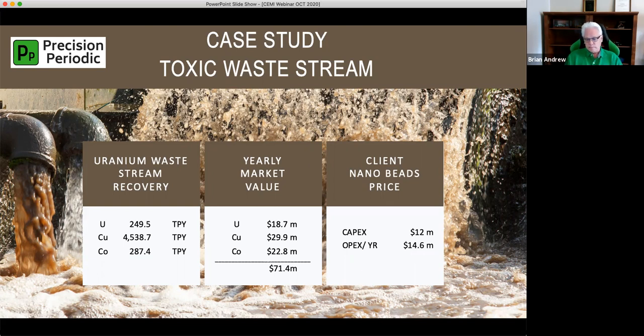And so it turns your waste into a profit center, which is pretty exciting. And this is true for the tailings we've looked at for acid mine drainage. When you go look at a tailings problem in America, you usually find it's leaching from a huge pile of something left there. And in America, for example, gold mines, a lot of the piles, the waste, the tailings are sulfide-based ores because they're difficult to handle. And with this process, you can go in and process the sulfide ores, keep the gold, take away the sulfur, and end up without an acid mine drainage problem. You start by doing the water first, and then sort of back into where the problem really is, and then go through the piles so they no longer leach the problematic material like arsenic, copper, sulfur, for example, in the case of acid mine drainage.